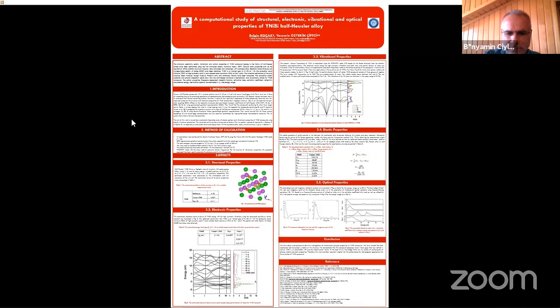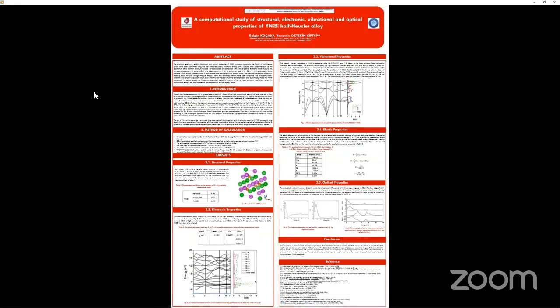The elastic properties have been estimated with the stress-strain method. Phonopy has been used to calculate phonon frequency. For the analysis of vibrational properties, the supercell approach has been used to calculate the phonons, with 2 times 2 times 2 supercells. The optimized parameters were calculated by the minimization and full relaxation of the unit cell. It is found that the obtained lattice constants are in good agreement with the experimental result.